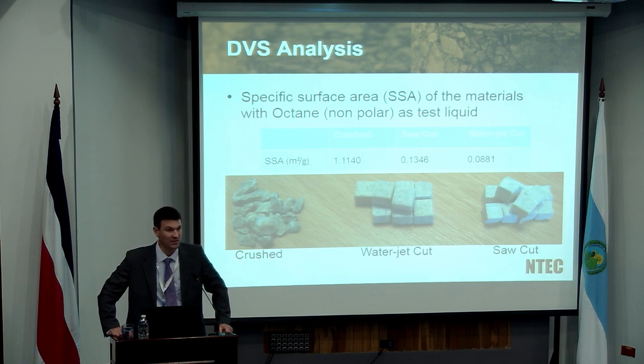And then we measured their surface-specific area using the same dynamic vapor absorption technique that we used when we measured surface energy. There are differences, and this is obviously a concern with this test because this becomes extremely difficult to mitigate against in terms of trying to understand the behavior. If you looked at your crushed aggregate, we're getting a value which is about 10 times higher than if we looked at those cubes, or the blocks, that have been produced using the cutting technique. And we looked at two different cutting techniques. We looked at a normal diamond edge saw, and we also looked at water jet cutting. They gave you very similar results. There's not much difference between those two, but it's important to realize that there is a factor of about 10. So although the profile wasn't different, the specific area is a factor.